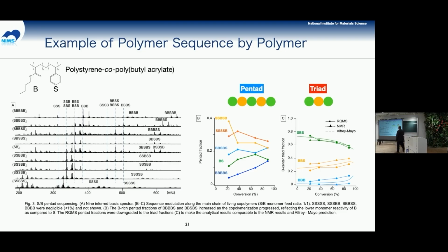machine learning supported mass spectroscopy analysis. However, even though we say this is our result, no one believes it, because no one has seen the conversion of the pentad before. So we converted this pentad data to the triad. The reason why we chose these polymers is that this polymer can be analyzed by NMR. Luckily, by comparing with the NMR data, and also the theoretical analysis, we converted the pentad data to the triad data. You can see that those data agree very well with these data. That means this data is also reliable.